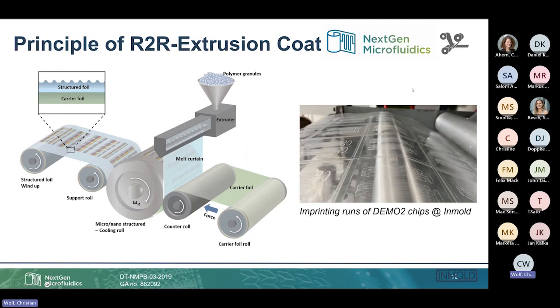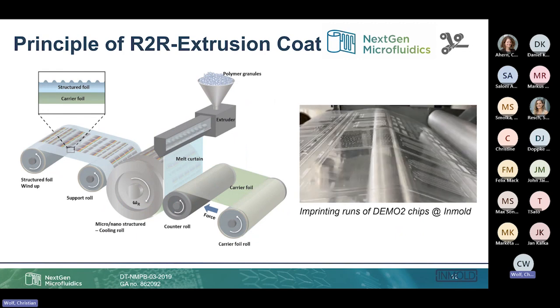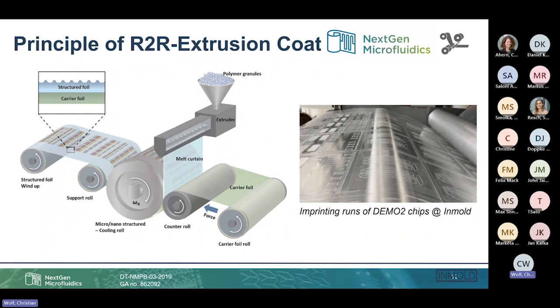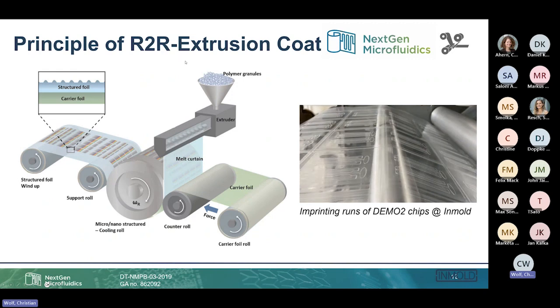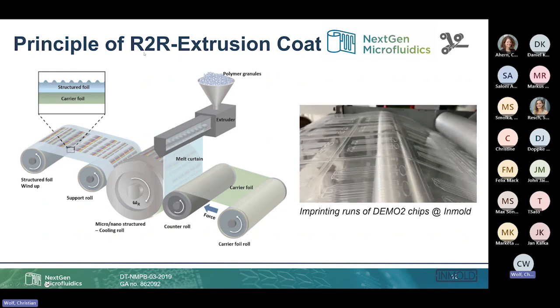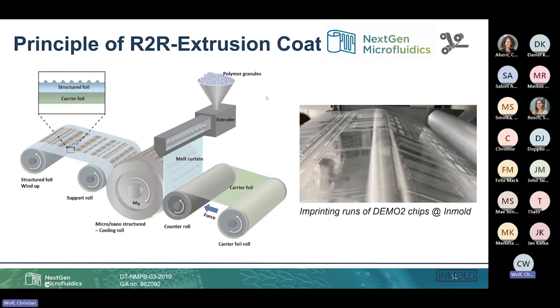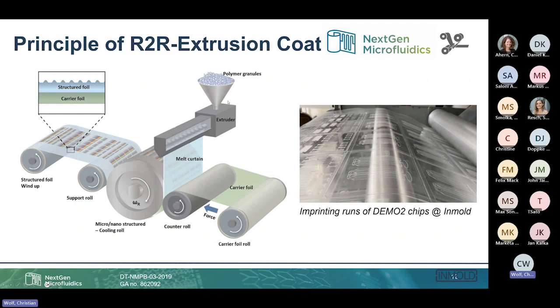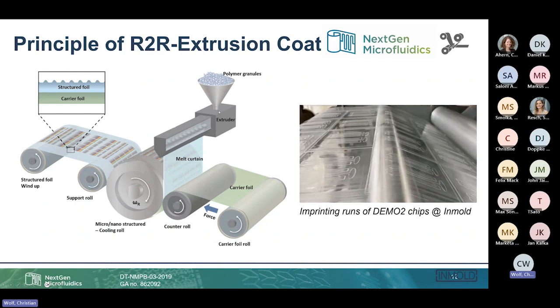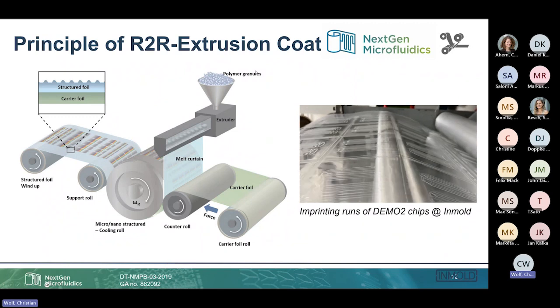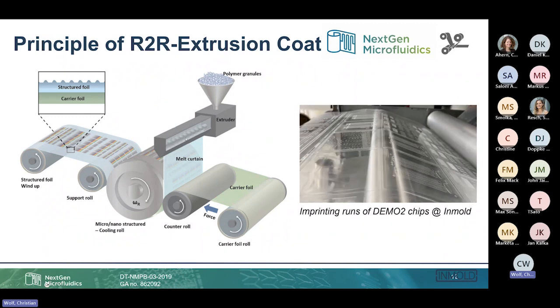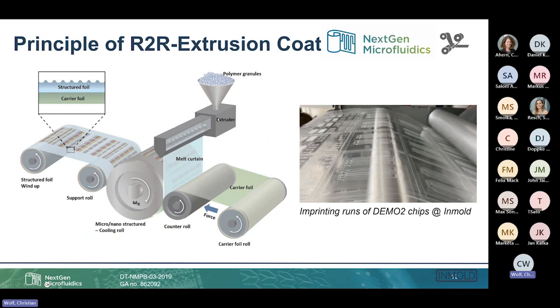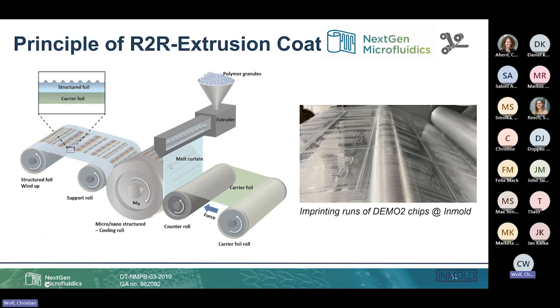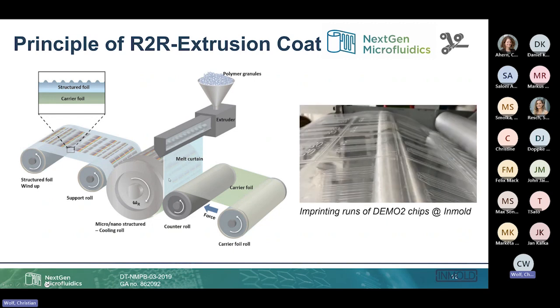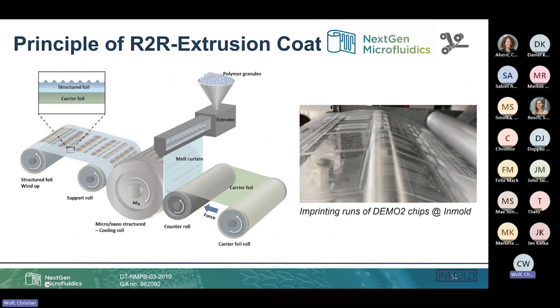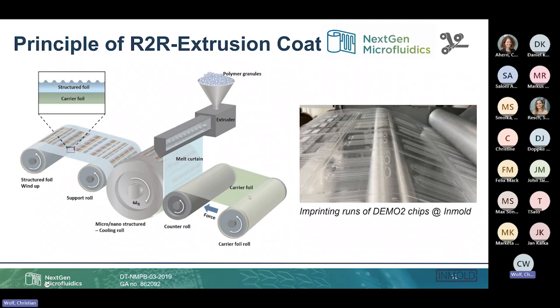Yeah, and as I told you, that's not the only imprinting process which we developed during the demo case. There was also a second methodology developed mainly by the company partner InMold. That was the so-called extrusion coating. It's a somewhat similar process, but the difference here is that you don't use any UV curing resins, but you use a thermoplastic polymer material instead, so something that gets soft when you heat it up. And there you also apply a thin layer of your melted polymer that's melted in an extruder and then extruded with a broad slit onto this carrier foil.